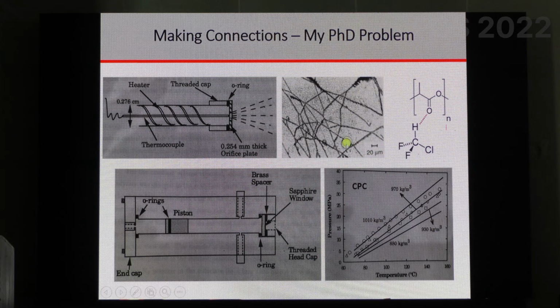So while I was looking at this, I was also interested in understanding why the polymer dissolves in a gas. This is unusual. So I actually built a high pressure bomb in which I would charge the polymer and the gas and pressurize it and then depressurize it and measure through this quartz window. I could measure the transmittance of the solution. And if it is dissolved, it's highly transparent. If it precipitates, it becomes turbid, and I could watch it with a video camera from this glass window.